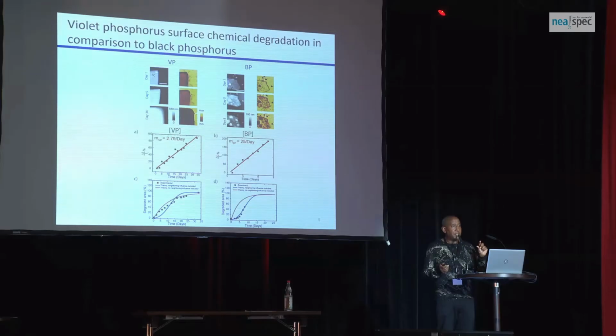But we think that that structure has something to do with the fact that it is more stable. If you measure with SNOM again over time, what you find is actually quite stable. So if you try to measure the thickness change over time and draw a line, the slope of the line is about 9 times steeper in black phosphorus compared to violet phosphorus. So time is the x-axis here. It degrades much slower and also differently in the way it looks, how it degrades.